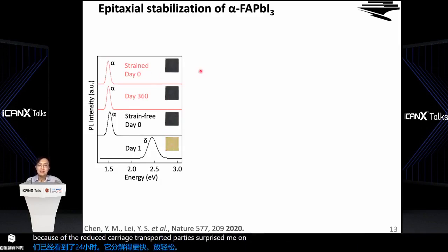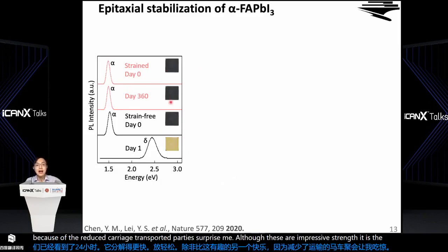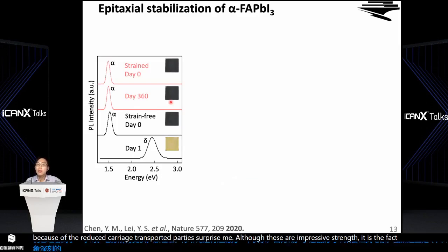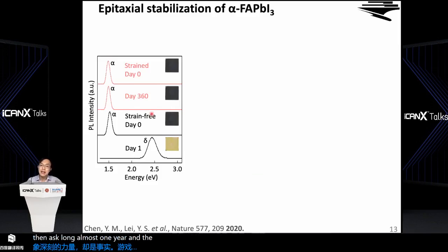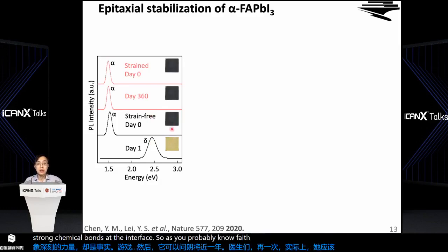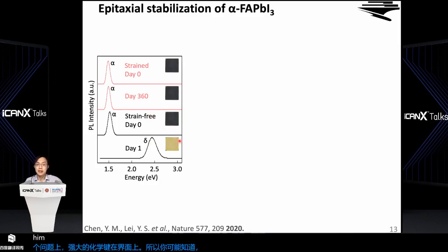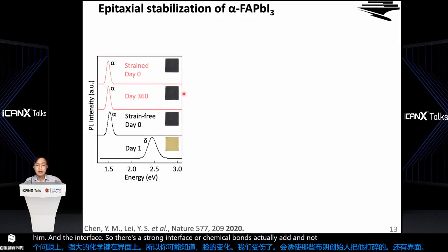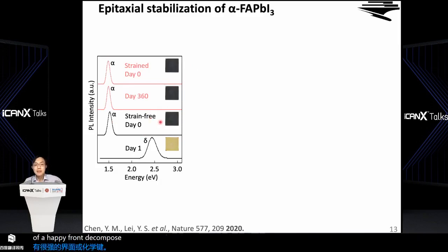Surprisingly, under this compressive strain, the lifetime of this alpha FAPI can be extended to almost 1 year. And we think this surprising enhancement can be explained by two factors. The major factor is that this epitaxial relationship actually clamps the epitaxial thin film on the substrate by a strong covalent chemical bond at the interface. As you probably know, phase change will induce bond breaking at the interface. So the strong interfacial chemical bond adds another layer of barrier that prevents the alpha FAPI from decomposition. So this is the major force that stabilizes this alpha FAPI.